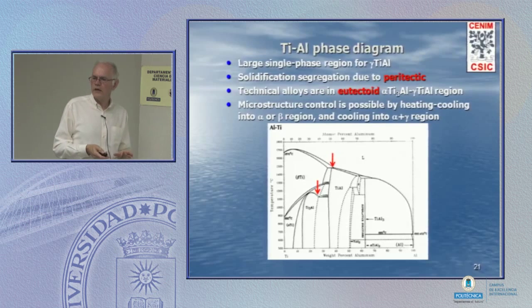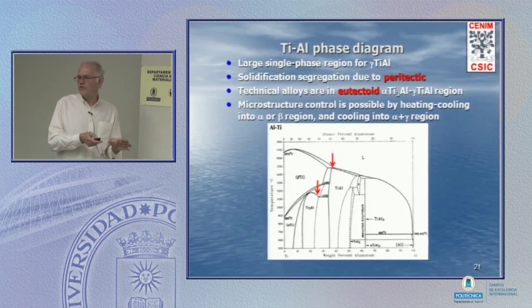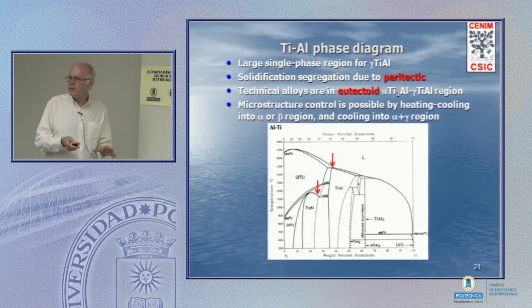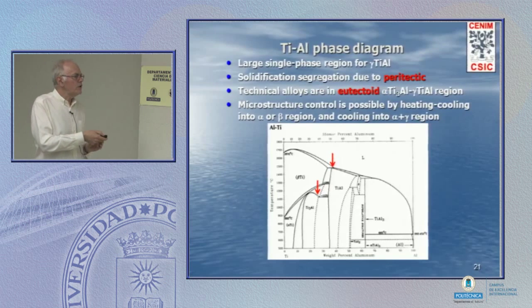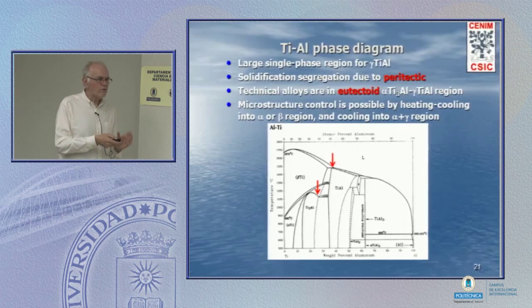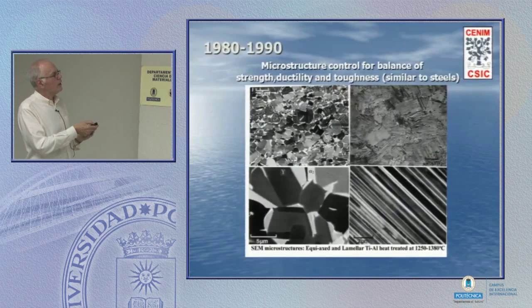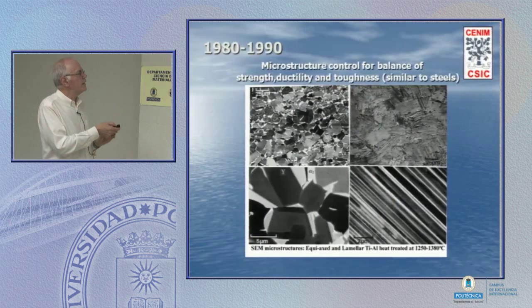Now, those that know about steels know that you have a eutectoid transformation, and what the steels people do is to heat their material up into the high temperature gamma, the austenite phase field, and then cool it down to obtain pearlite or martensite or whatever. The eutectoid temperature offers you the ability of heat treatment for microstructural control and then property control. It's very important. Now, here are the two types of microstructure that you can get simply by heat treating.